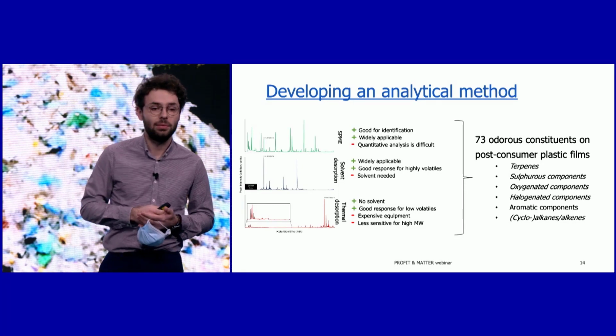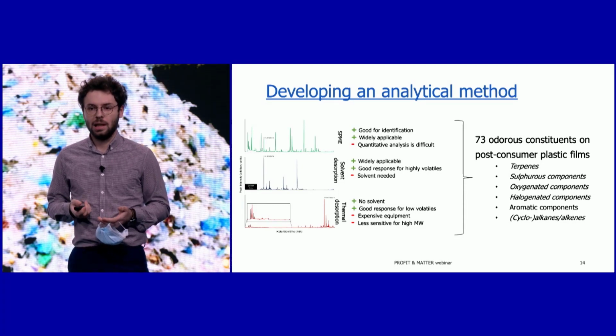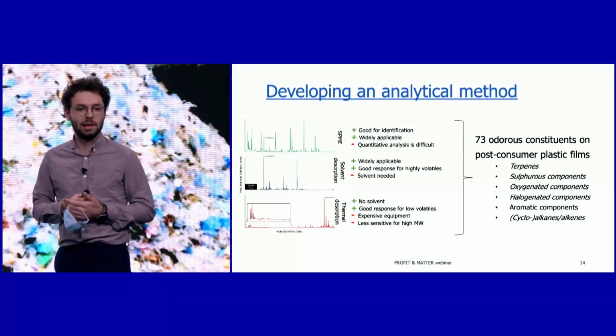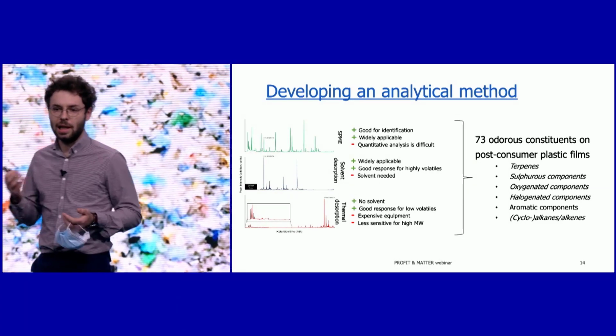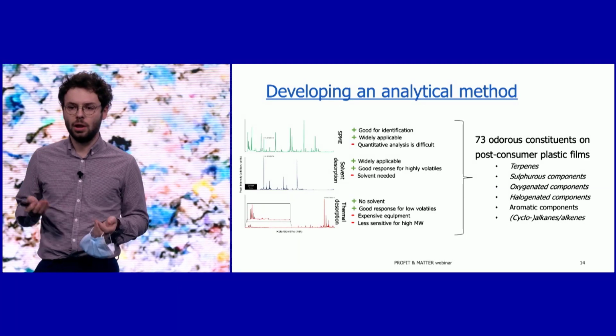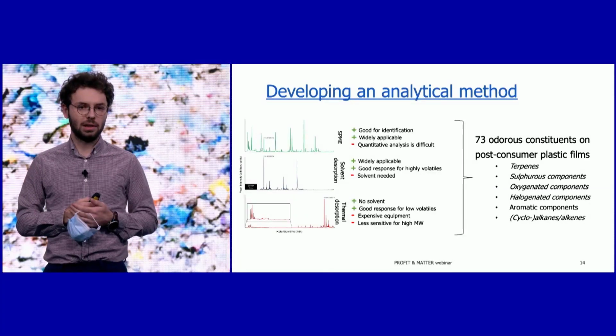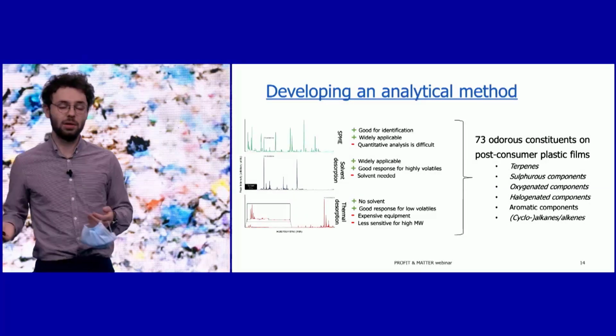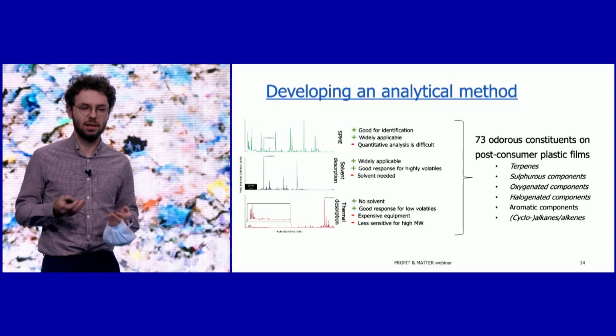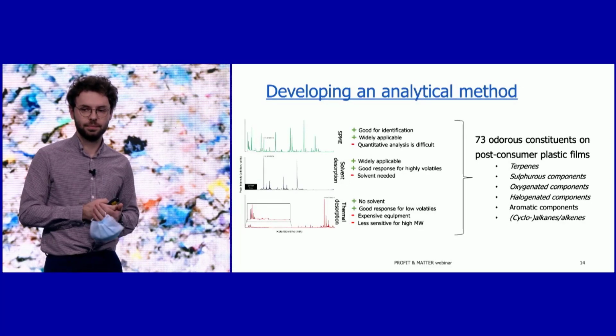The second technique that we tested was solvent desorption, and this technique is also widely applicable. Moreover, this technique shows a good response for the highly volatile components. But for this technique, of course, a solvent is needed, which is again a disadvantage.